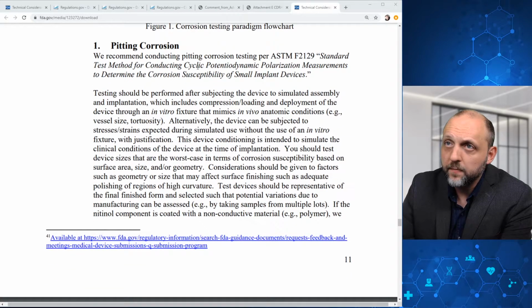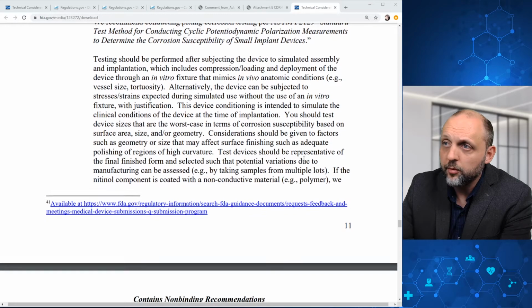In terms of pitting corrosion, FDA recommends conducting testing per ASTM F2129. Testing should be performed after subjecting the device to simulated assembly and implantation, which includes compression, loading, and deployment of the device through an in vitro fixture that mimics in vivo anatomic conditions. And alternatively, the device can be subjected to simulated use without the use of an in vitro fixture with justification. And here, the device conditioning is intended to simulate the clinical conditions of the device at the time of implantation. And you should look at worst case scenarios in terms of corrosion susceptibility based on surface area, size, and geometry.